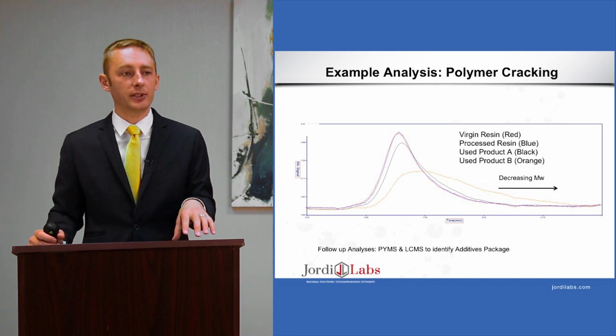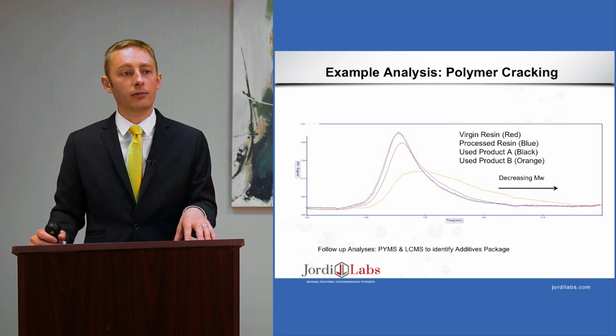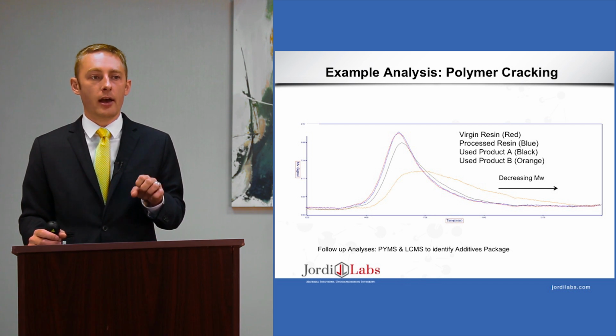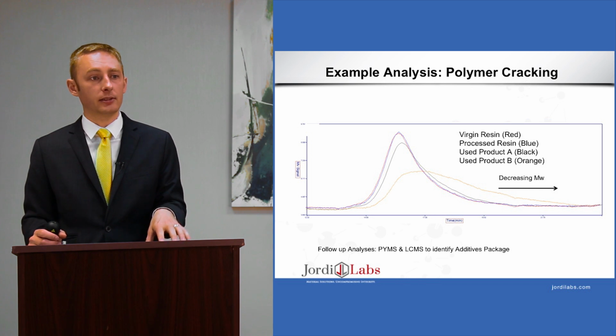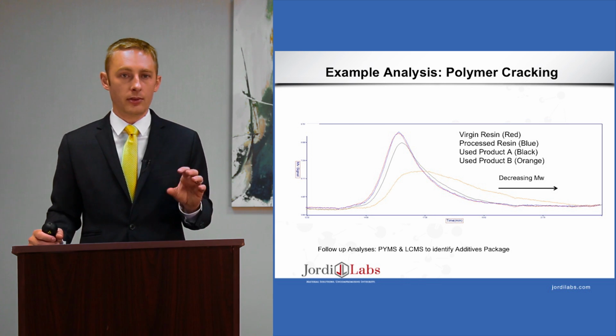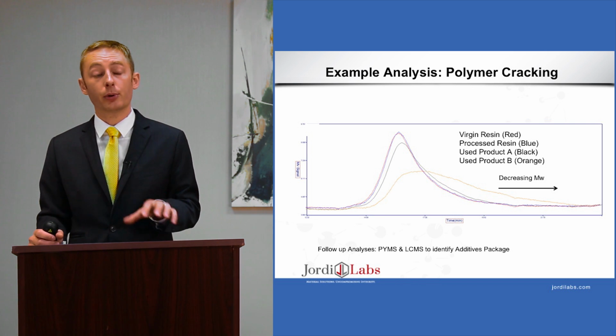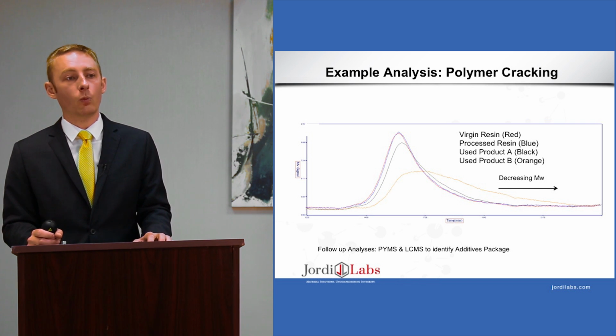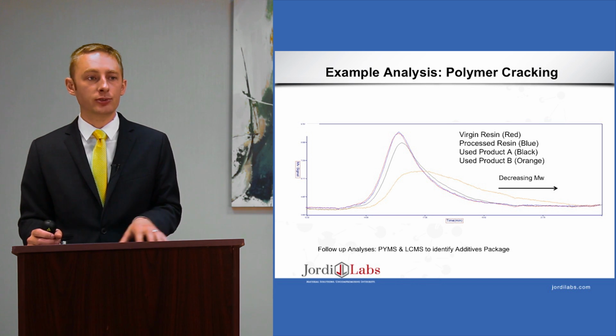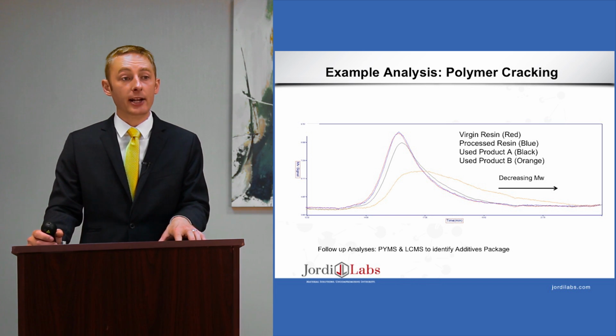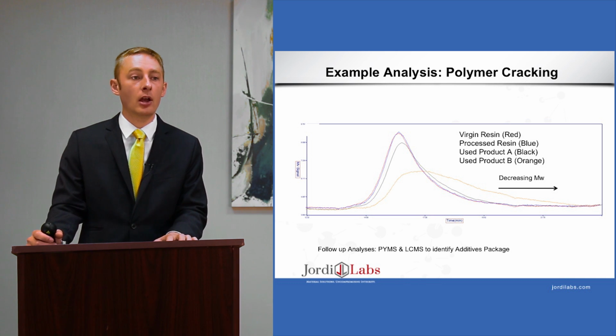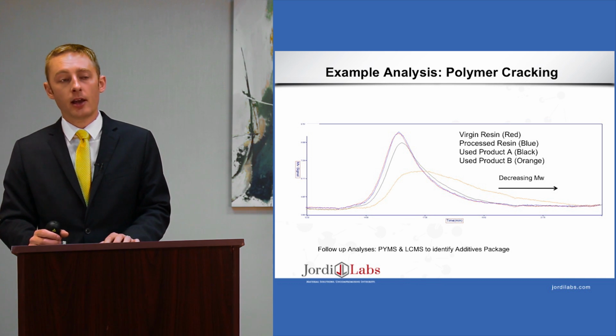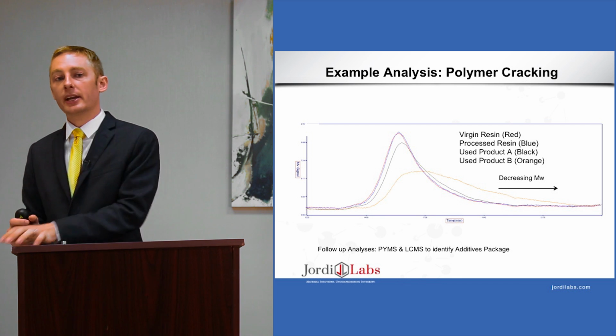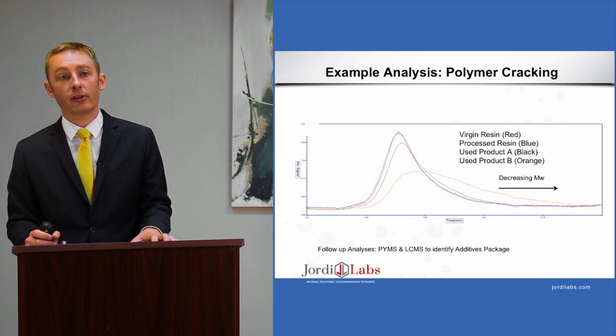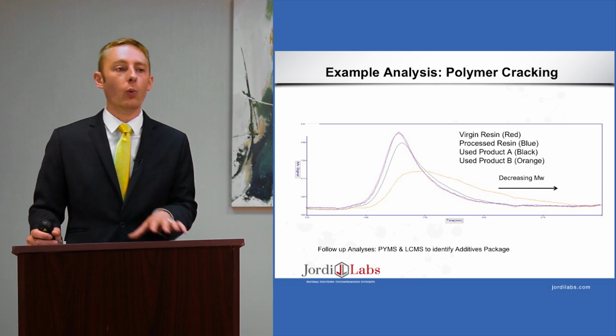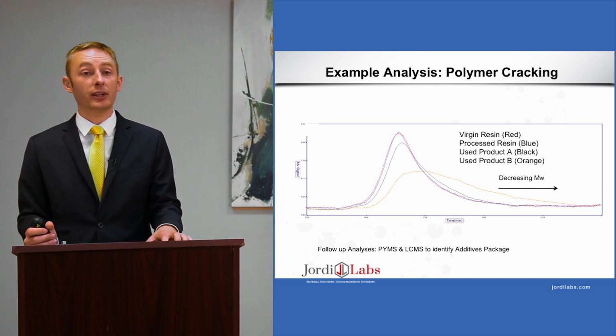And so what we're able to show in this case here is that the molecular weight of the virgin resin, of the processed resin, is effectively unaltered. So the raw material is fine. The production process is fine. Where we start seeing a problem is after the product's been used in a few different ways. And so the black trace and the orange trace, in this case right here, show a decrease in molecular weight of the product. And so this informs our next decision of, do we need to identify the additives that are present in this sample? What's the next thing that we have to do to fix this problem?